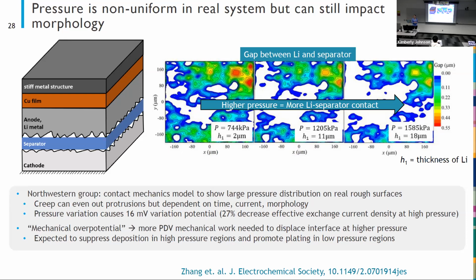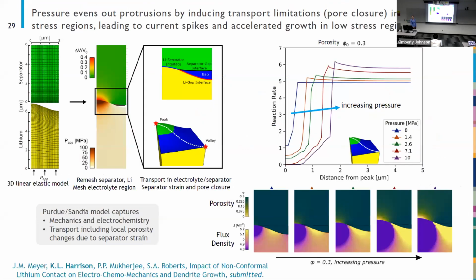The way we can think about that more physically is that when you're needing to displace an interface, so let's say we have lithium under pressure in a certain area, if you want to plate more lithium in that area, you have to move that interface. That takes work, pressure-volume work. And so it's easier for the lithium to deposit in the low pressure region because you don't have to do additional work in order to move that interface. So that gave us some insight into how the pressure can control lithium growth, even in a real system with rough interfaces. And that was a really, really nice model.